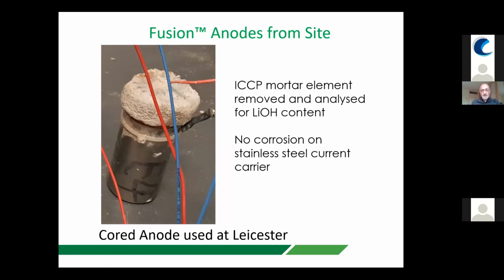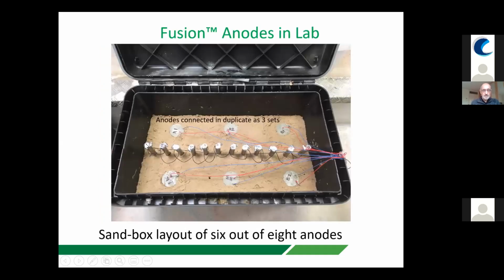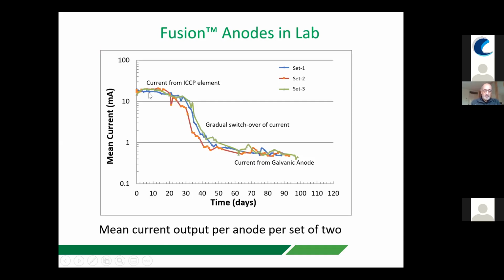We wanted to see whether driving current through them, or through some of them, would cause any pitting on the stainless steel, and it was clear that that wasn't the case. And that was primarily because of the encasing mortar that was very highly alkaline. We then embedded them in a sand box, connected them to individual steel bars, and continued to monitor them. And we can see that obviously the ones that were not connected up inside and then connected in the laboratory, they produced that initial current. Then there was a gradual drop, and then the galvanic anodes took over. And this is actually happening all by itself. So as soon as the battery runs out, then the galvanic anodes kick in and they maintain the lower current density.